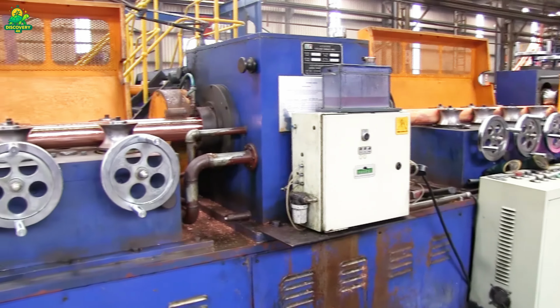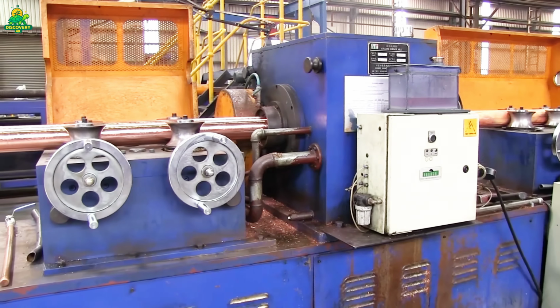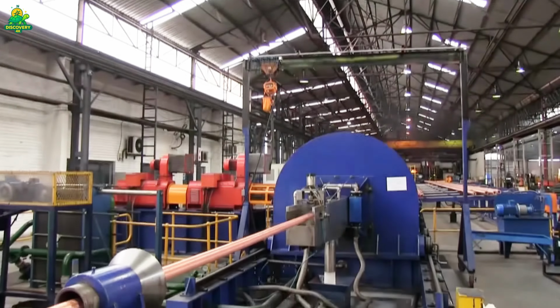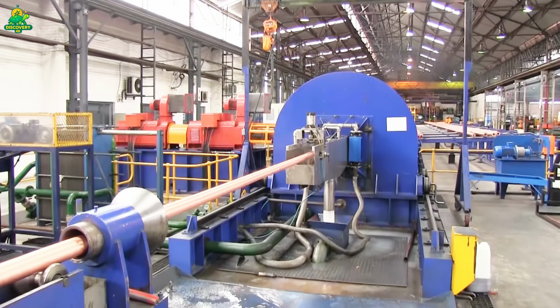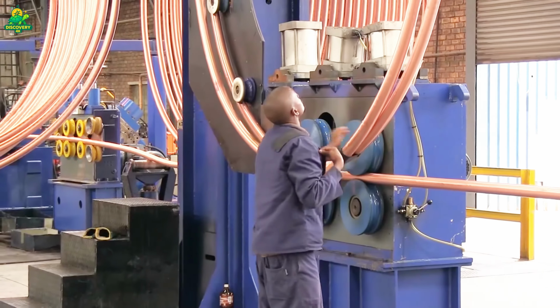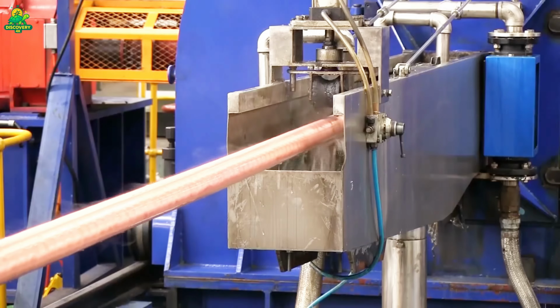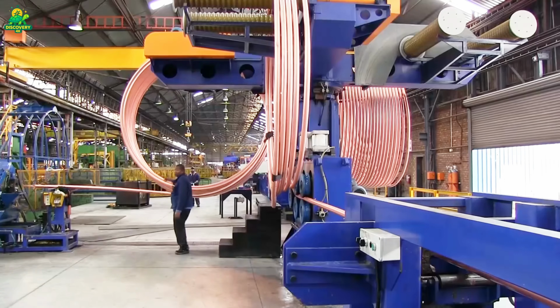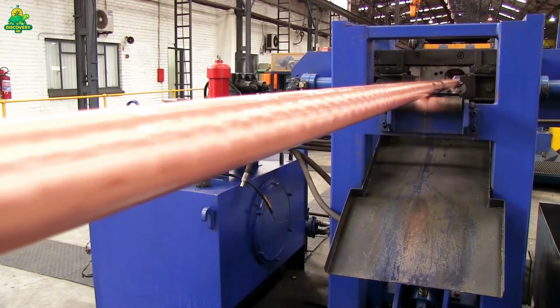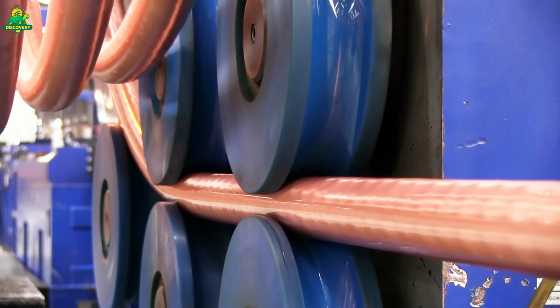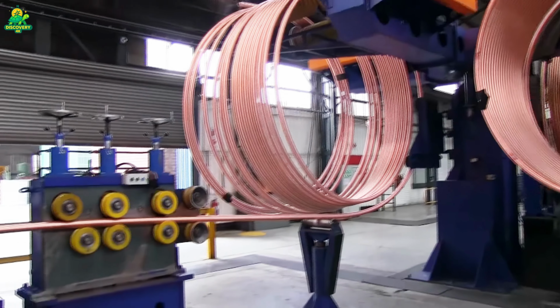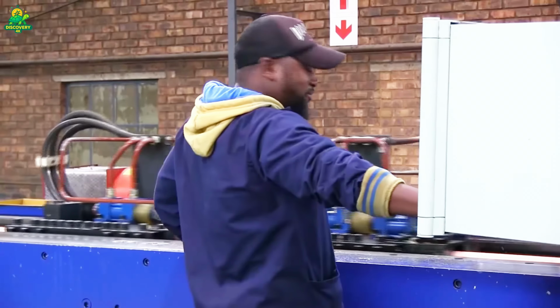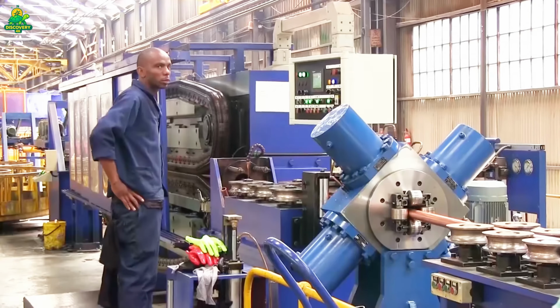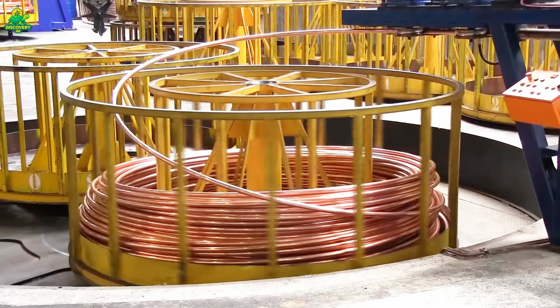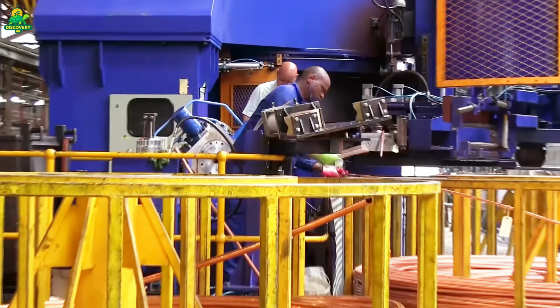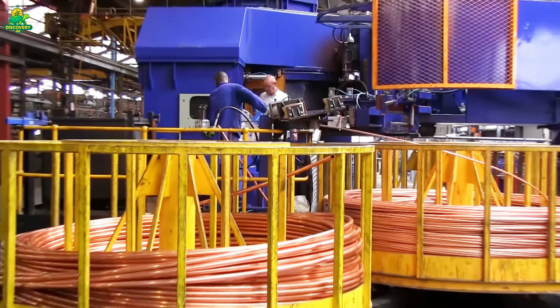Workers watch closely as lasers measure the diameter, wall thickness, and uniformity of every inch. If something's even a fraction of a millimeter off, the tube is automatically rejected. The copper cools quickly as it moves along conveyor belts, slowly turning from fiery orange to metallic red. This extrusion line can produce hundreds of feet per minute, creating miles of copper tubing every hour.